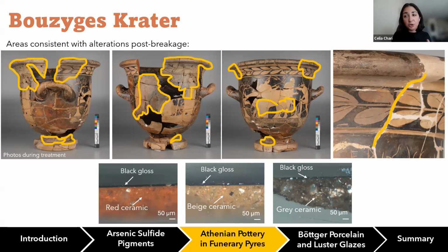we learned that during these practices, a common thing would have been to break these craters directly onto the funerary pyre. So the crater itself would have shattered into pieces, and completely by chance, depending on where those sherds landed with respect to the burning body, it could have been more reduced by high temperatures or less reduced. And we see that there isn't just two options. There really is a gradient of different levels of reduction that we're observing, from the red ceramic to it turning slightly more beige and then more gray in color.